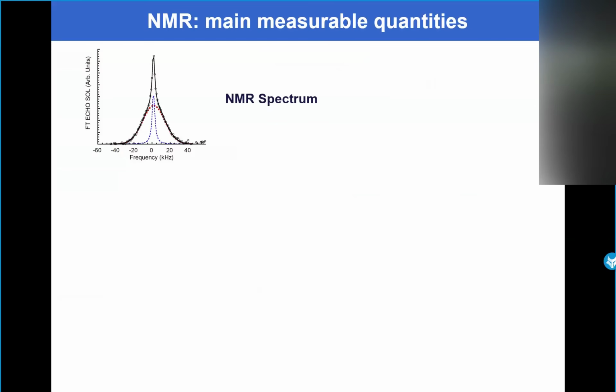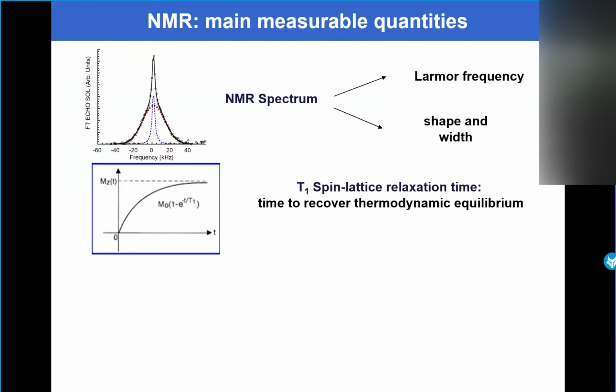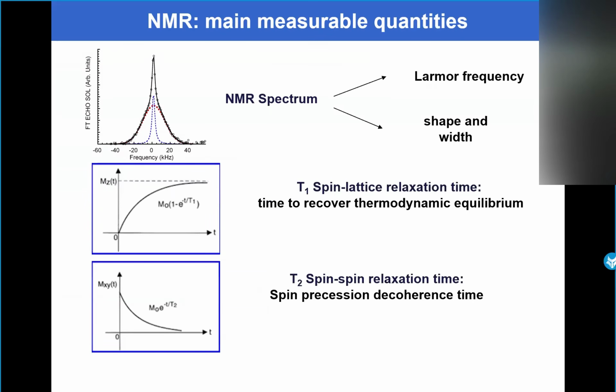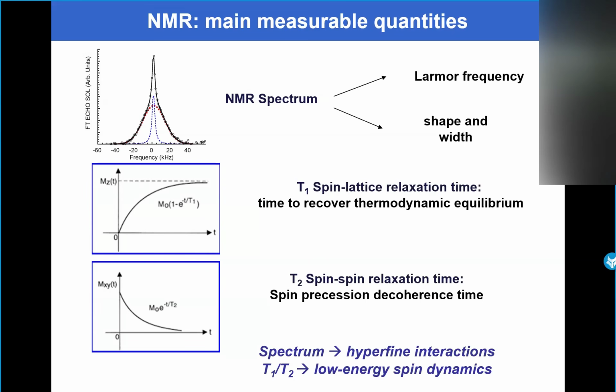What are the main measurable quantities? Typically, the NMR spectrum, and from the Larmor frequency, as we already mentioned, and also from the shape and the width, we can get physical information on the system, and also from what we call the spin-lattice and spin-spin relaxation times. This is in addition, for instance, to the Mössbauer technique. Today we are not going to talk about this, but in general, from the spectrum we can get information regarding the hyperfine interactions, while from the relaxation time we can get information regarding the low energy spin dynamics.